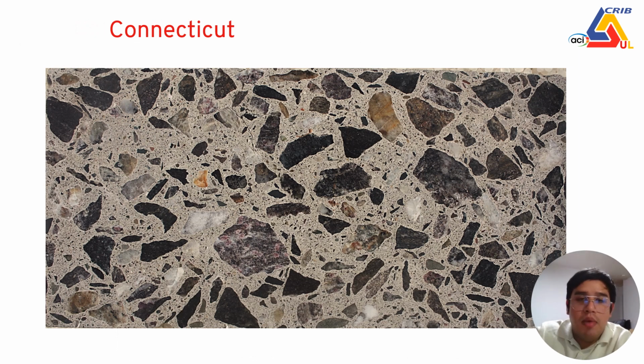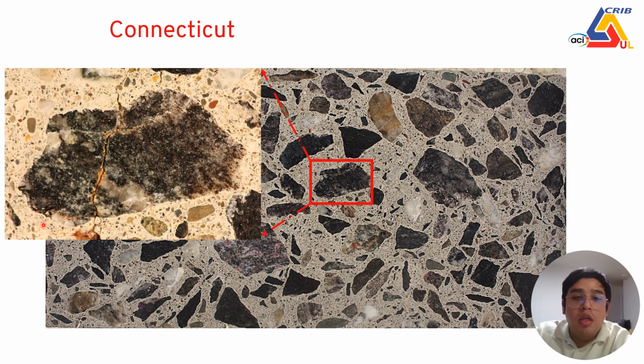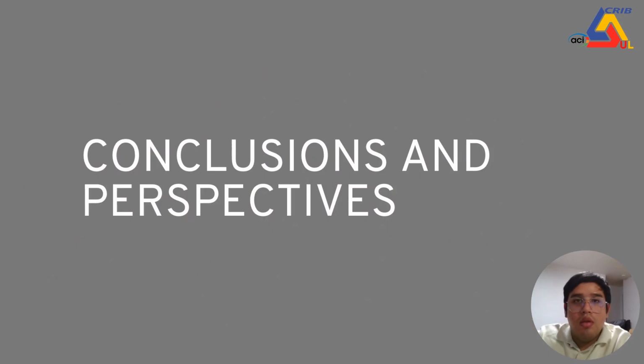At the same time, I would like to share with you this polished section of the concrete with the Connecticut aggregate, a sulfide-bearing aggregate. It's difficult to see, but there is already cracking after 35 days of electromigration treatment. And if we zoom in, we can see clearly how these open cracks in the aggregate transfer to the cement paste with rust products surrounding the crack. Now I will present some conclusions and perspectives.